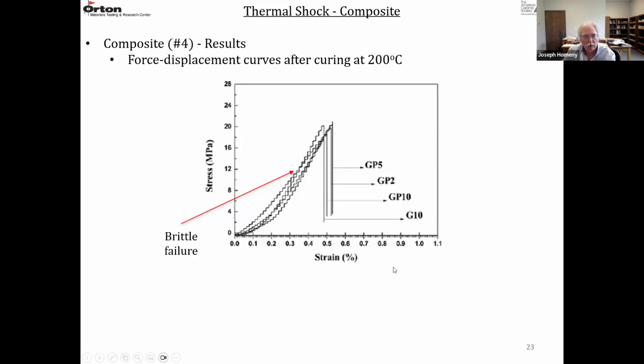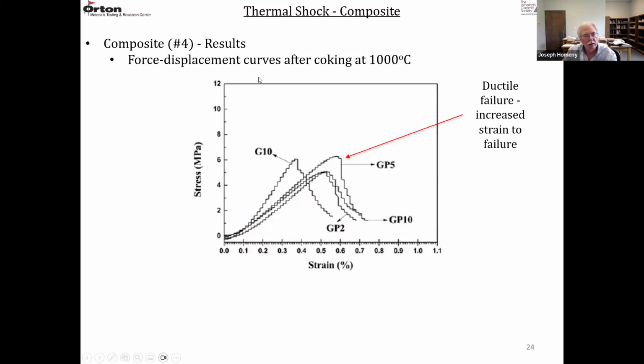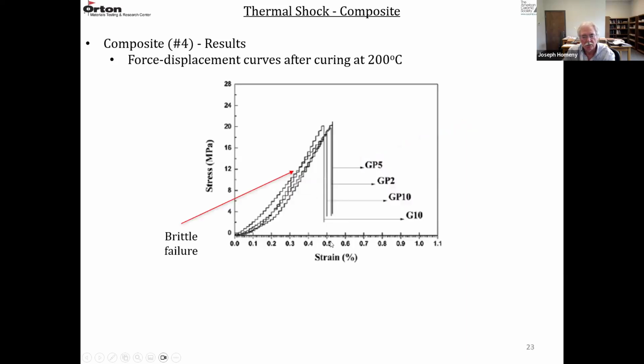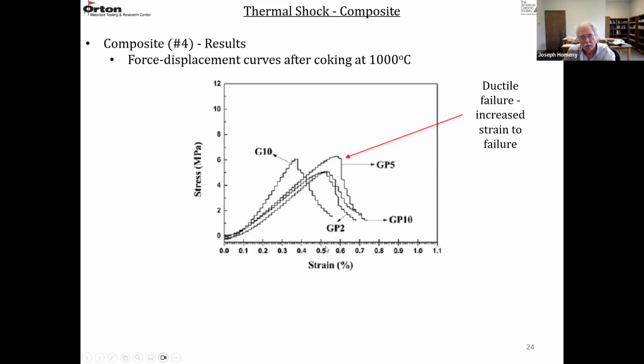It's a brittle material. Then after you coke it at 1000 degrees C and you generate a stress strain curve or a load displacement curve, these all become nonlinear. And then the fractures tend to be stable. There's no rapid drop off in the load at a particular strain. They tend to be more stable. So now it's not really a brittle fracture anymore. It tends to be more ductile. And then the strain to failure becomes larger. These were about 0.5%, and these are reaching maybe closer to 0.8%.